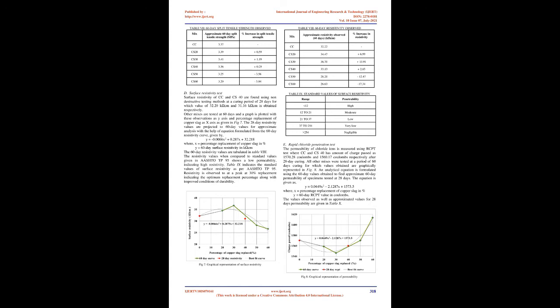Split tensile strength of CC and Cs40 is observed at 28 days, which is 3.37 and 3.35 respectively. All other mixes were tested at 60 days. A graph is plotted with percentage of copper slag replaced and observed split tensile values as shown in Fig. 6. An equation is formulated with the 60-day split tensile strength to find the approximate 60-day strength of specimens tested at 28 days for an impartial analysis. The values obtained are above the target strength desired, and a slight strength gain for 28-day samples is observed.